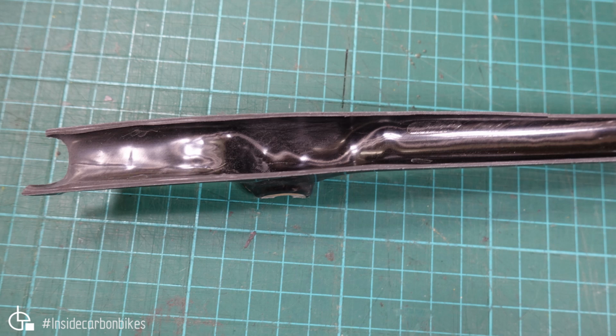And then here again you can see some of the compaction variation, particularly this area here, which looked like it didn't get any compaction at all. You can see the fibers almost look dry, it indicates that you haven't had any pressure on there during the cure cycle to promote flow of the resin during cure. So yeah, that's not ideal. It's not a huge deal breaker though.